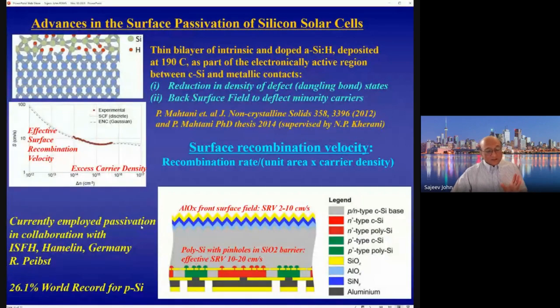Another approach that we're following with the help of a group in Germany, which actually set one of the recent world records for silicon solar cell efficiency of over 26%, is to deposit a layer of aluminum oxide on top of silicon. That also creates a strong electric field that can deflect what are known as minority carriers from the surface, and also leads to very effective surface passivation, leading to velocities on the order of 2 to 10 centimeters per second. And on top of that is a silicon nitride layer and a silicon dioxide layer that provide anti-reflection coating.